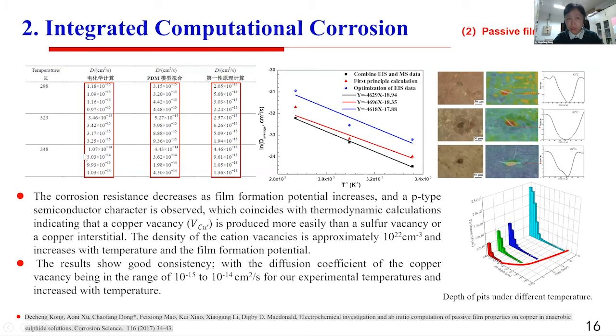From the table, we can see the diffusion coefficients from the electrochemical method, this list is from the PDM model, and this one is from first principles calculation. The results show very good consistency with the diffusion coefficient of the copper vacancy, in the range of 10 to the minus 15 power to 10 to the minus 14th power. So that is very good for our experimental temperature